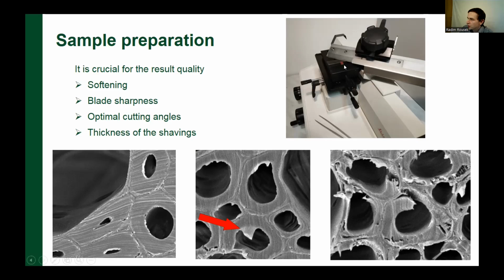The next important thing is a sharp blade. It means if you need a really nice surface, you need to do the last cut with a fresh blade which has never cut before. And very important is also cutting angle. I will show you more on the next slide. And also, thickness of the shaving can influence the surface quality. If the shaving is too thin, usually the surface is more damaged.